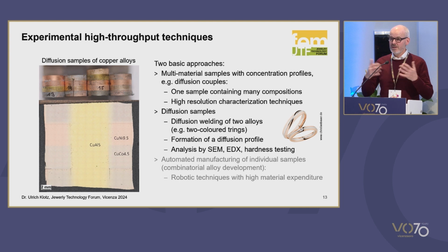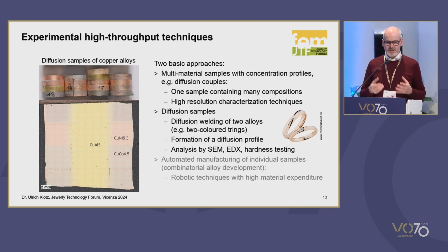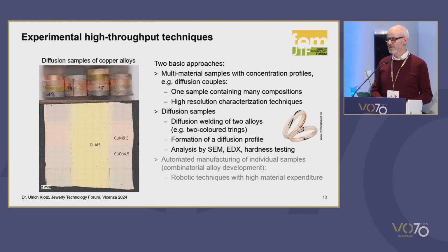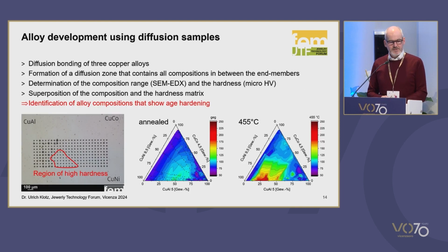place. And by diffusion, the compositions of these different alloys are mixing. So in this diffusion zone, which is maybe 1 millimeter wide, we get a mixture of all the 3 alloys in this case at the contact point, and we get hundreds of compositions within a very small range. Now we have to measure these compositions, and we can do this in the electron microscope and by microhardness measurement. And this is what we've done here.